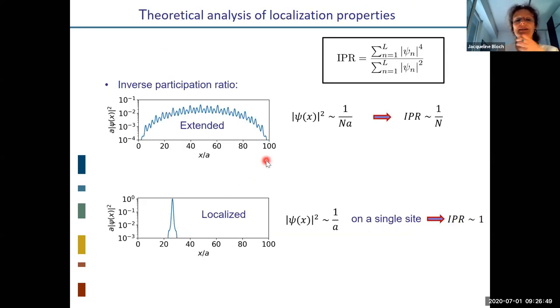To study this localization property, you can define a quantity called the inverse participation ratio, IPR, which is going to describe the localization properties of your state. If you have extended states, this IPR is going to be equal to 1 over N, N being the number of atoms you have on your chain. So it goes to zero if you have an infinite chain. Whereas if you have localized states, the IPR will be close to one.